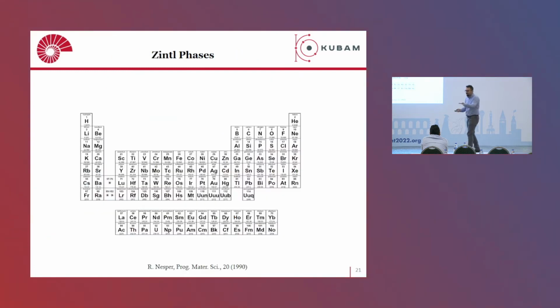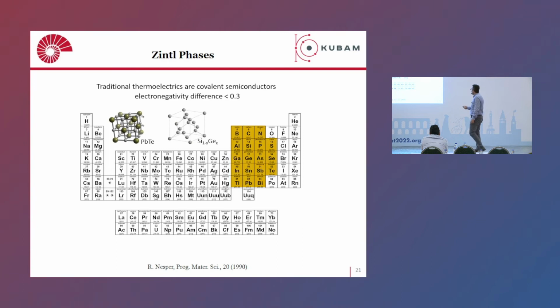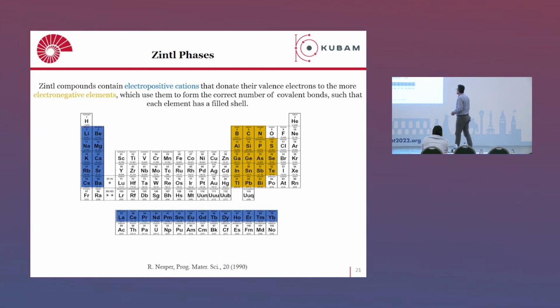So now let me just tell you what a Zintl phase is. Maybe this is the first time you are hearing about it. Most traditional thermoelectric materials like lead telluride, silicon germanide, these are the materials used for space applications. They are covalently bonded materials, typical covalently bonded materials, and they are composed of these p-block elements. Zintl compounds contain both electropositive cations, as you can see here, that donate their valence electrons to the more electronegative p-block elements, which use them to form the correct number of covalent bonds such that each element has a filled shell. Which means it is kind of an electronic transfer from the cation to the anion.